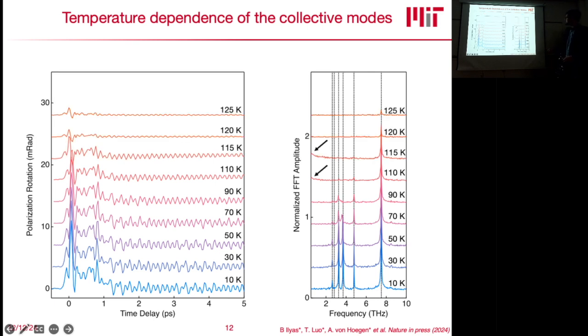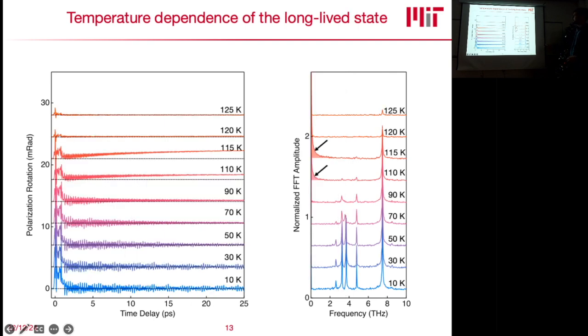And this is actually very interesting, that around where this coupling is proposed to be stronger, we see this very small upturn down here at very low frequencies. And if you now increase our time window, you will actually see that this small upturn is actually a pretty big upturn in the FFT, and you also get this quasi-static offset, which only appears very close to the transition temperature of this material.